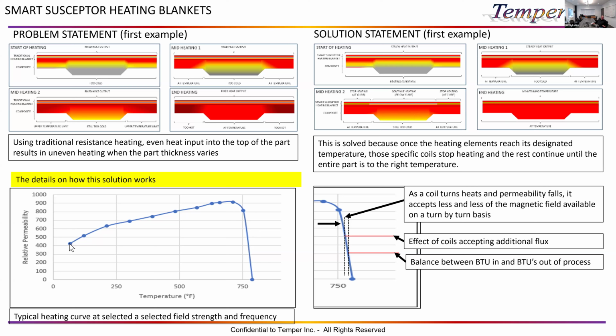Now, to dig a little bit deeper, and this is as far as we're going to go here, into how it works. It's relative permeability, which changes with the field density and with temperature. So for instance, in this example, this is a material that's going to become non-magnetic at, say, 780 degrees. It's not magic, it's just physics. Let's say you had a tool with a heat sink. The heat sink would continue to heat here, and where it was thin or where there was not much of a heat sink in the material absorbing the heat, it would stop heating here. And so you would end up with this range. To get more into that, it'll take some more time, so we're going to keep moving on.